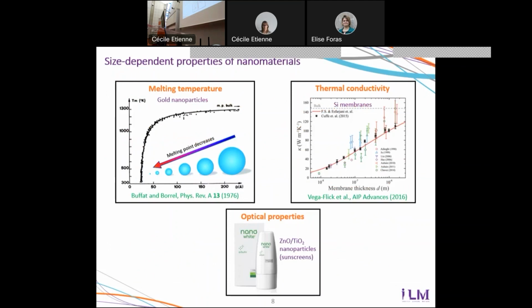So to give you a few examples, actually, the melting temperature of gold nanoparticles. For large nanoparticles, it's the same as that of gold, so a bit more than 1,000 degrees. For very small nanoparticles, for example 5 nanometers, the melting temperature becomes much lower. It's much easier to melt nanoparticles.